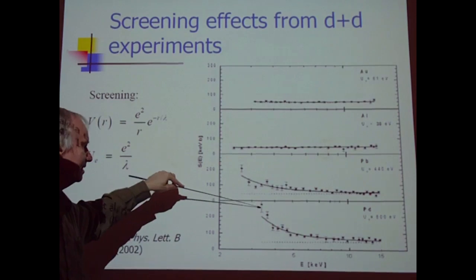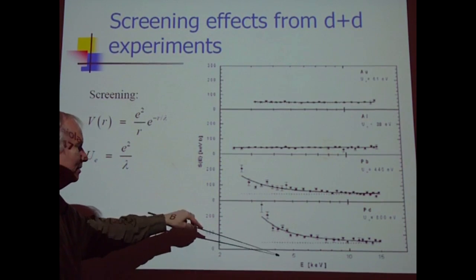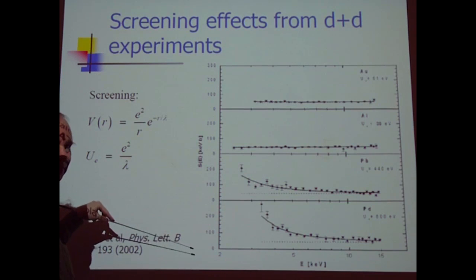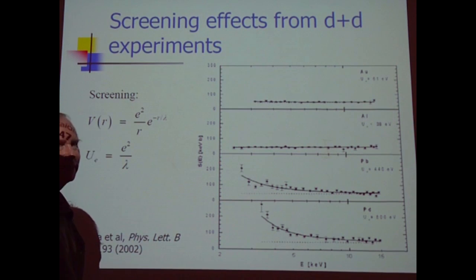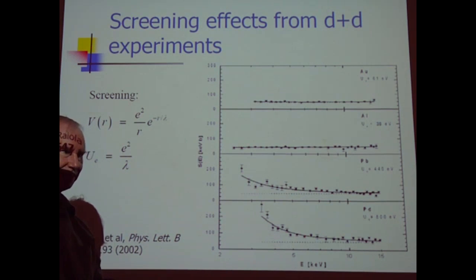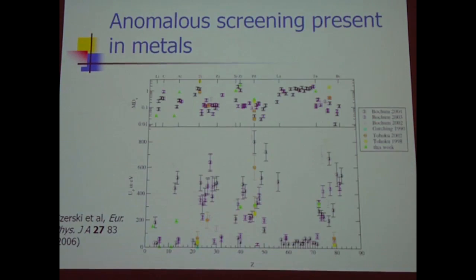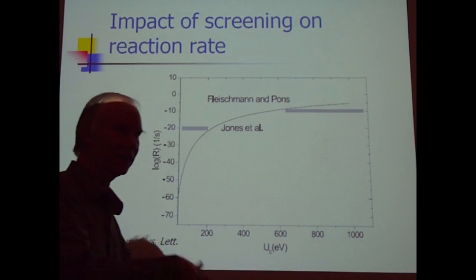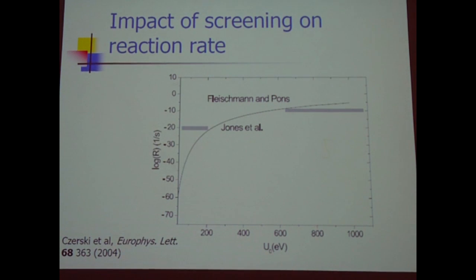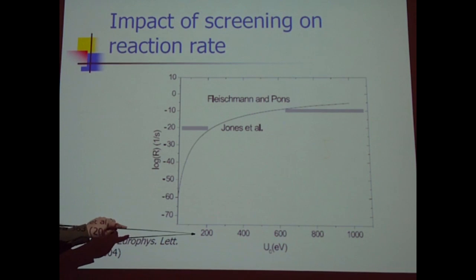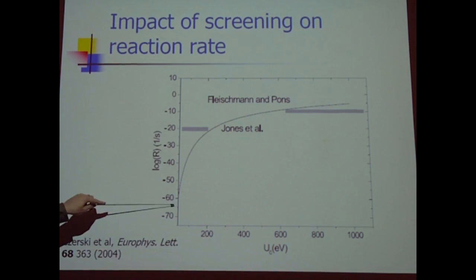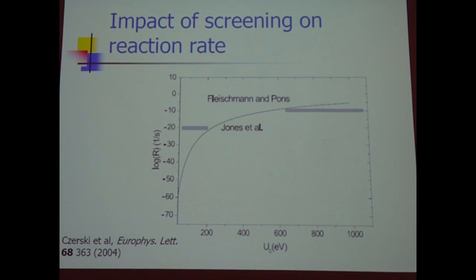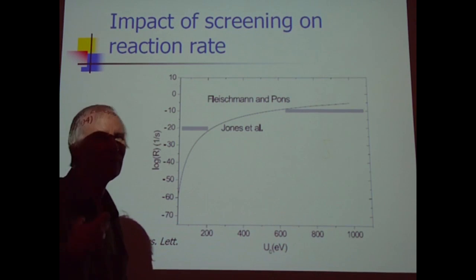And then if your screening number is 800 volts, what happens is that here you're getting bigger and bigger and bigger, and this is up at a few keV. And by the time you get down to small numbers, this is like orders and orders of magnitude. So basically the orders of magnitude we saw in the other plot, this is just extending that curve down to low energy. So the good way to think about it is here's the screening energy and here's the change in tunneling for the D2 molecule kind of problem. Not change in tunneling, change in rate, which depends on e to the minus g squared.